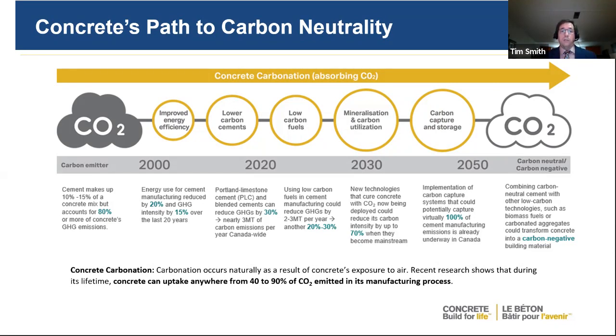But another point that I wanted to make is that concrete will naturally start to carbonate because it wants to take back some of that CO2 that it released in the process of creating the clinker. Studies have shown that the uptake can be between 40 to 90% of the CO2 that was originally emitted during the creation of the cement. So we do know that carbonation is something very positive, and we need to take that into account when we're looking at our designs.